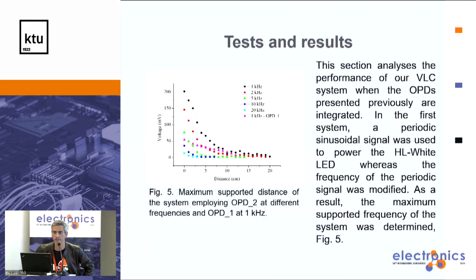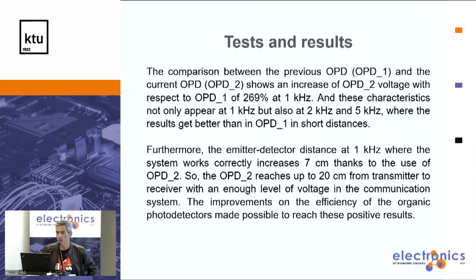And now the part of the results. First of all, we are going to compare the results in this research with the previous research. We can improve the results not only at the same frequency, 1 kilohertz, but also at 2 or 5 kilohertz, and with different distances. We have an increase of about 269% at 1 kilohertz, and we can obtain better results also at 2 kilohertz and 5 kilohertz. And we can increase the distance between transmitter and receiver up to 7 centimeters, for instance.